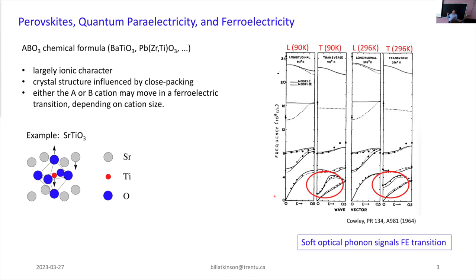So the branch that's circled is the one that corresponds to the eigenvector on the left. And it's got one dispersion at room temperature and a different dispersion at 90 Kelvin. And you can see that it's going soft at the zone center. Okay, and that tendency towards softness is the signal that you have an incipient ferroelectric transition. Once that phonon goes to zero frequency, you get a second order phase transition to a ferroelectric phase. And essentially it just means that this phonon freezes.